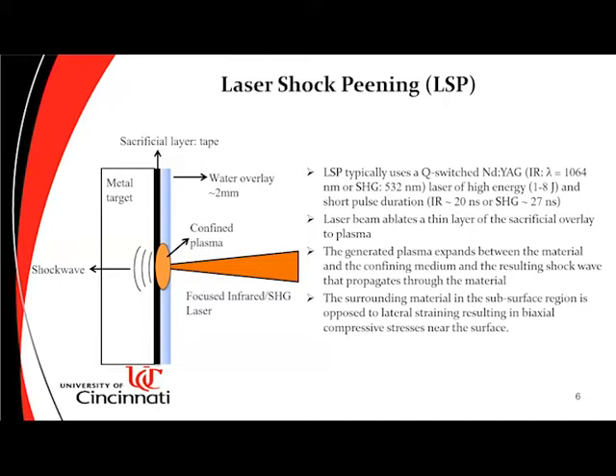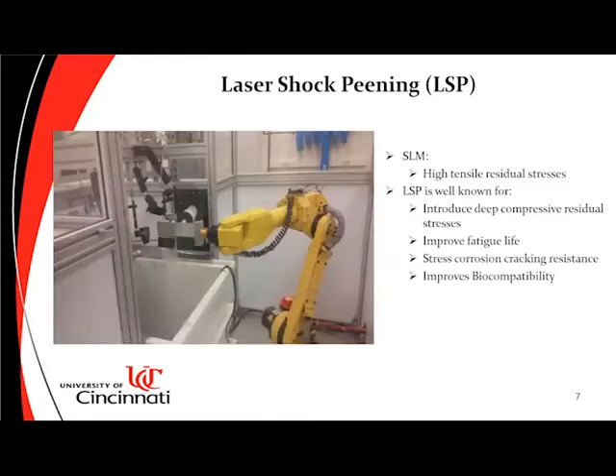This is a schematic of the LSP process we use. This technique uses a high energy laser beam that ablates a thin superficial layer, which is usually the tape, and this generates a plasma that is confined by the confining medium, that's the water, resulting in a shock wave that propagates into the material, creating compressive residual stresses. There are a number of parameters we can vary to produce different results. This is the setup we have in the lab at the University of Cincinnati. As I've already mentioned, the additive manufacturing SLM process generates tensile residual stresses that reduce fatigue life, whilst LSP introduces deep compressive stresses, which improves fatigue life and other properties.